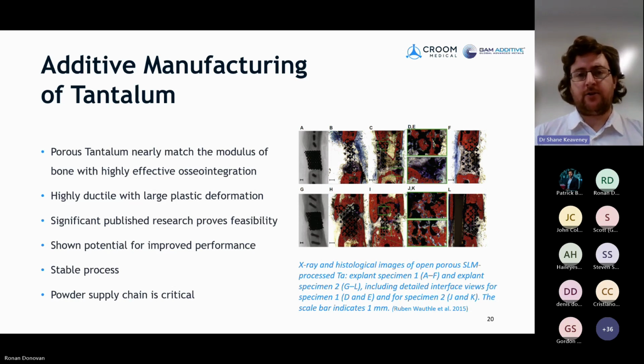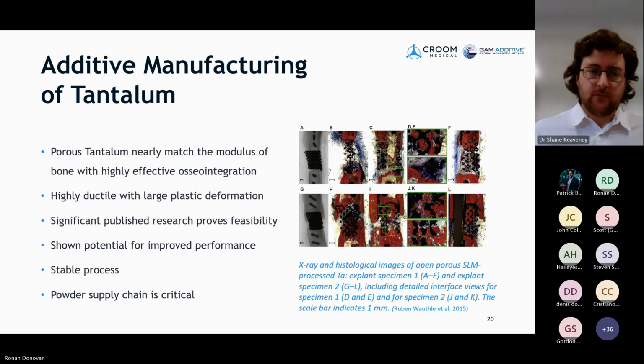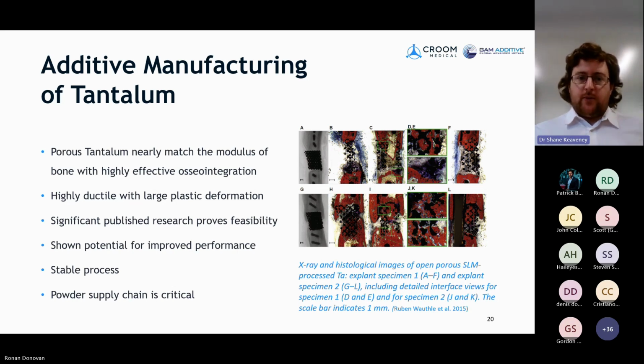SLM in particular, due to the feature sizes that we can achieve, and with the porous structures that we're trying to achieve, we're looking at very small feature size of maybe 200 microns. Now in terms of additive manufactured tantalum, as you've seen, there's a good bit out there in the literature over the last couple of years, and it's increasing. So there's a trend there of more investigation into it. So for us as an actual subcontract manufacturer rather than an academic research institute, we were keen to see, could we replicate the results seen in the literature at a scaled up industrial level to then offer to our customers.